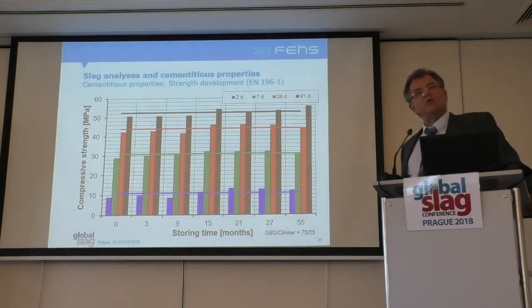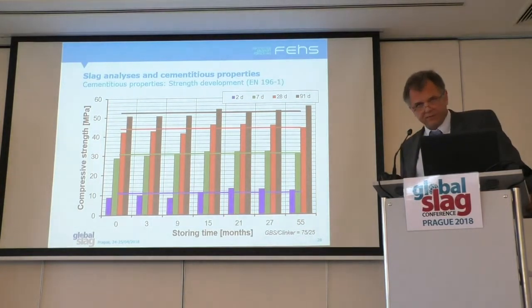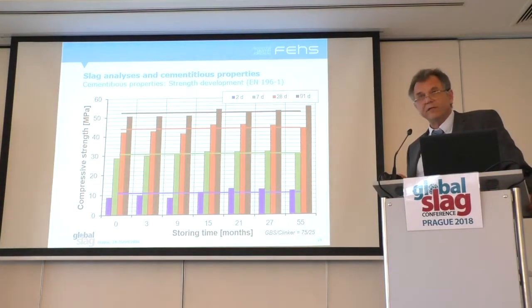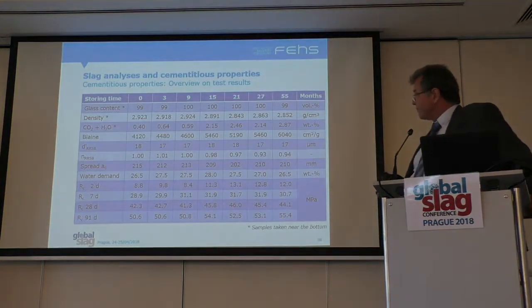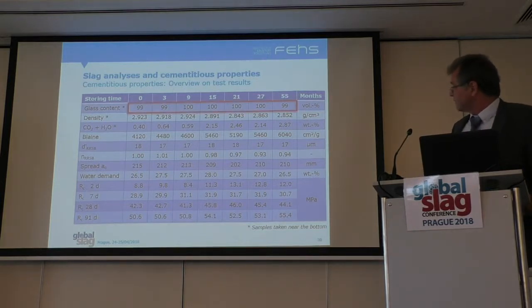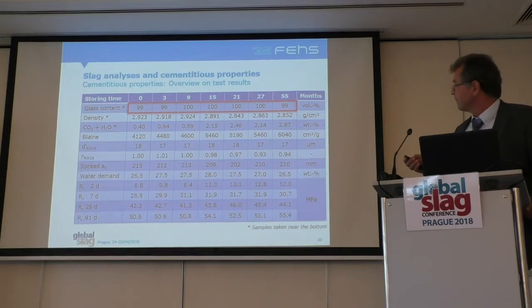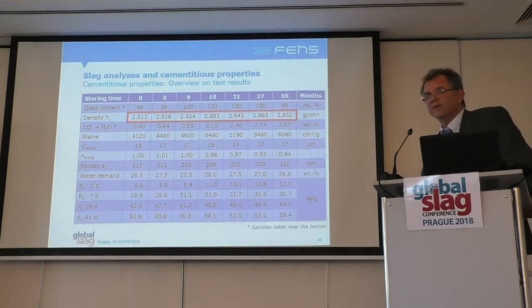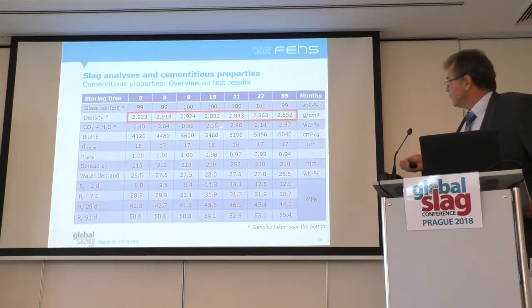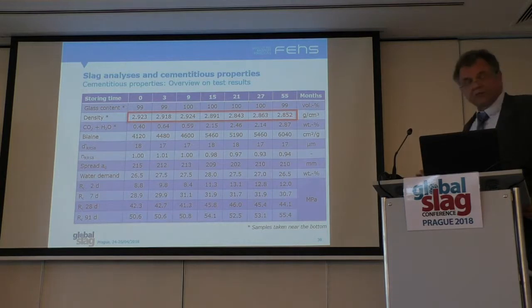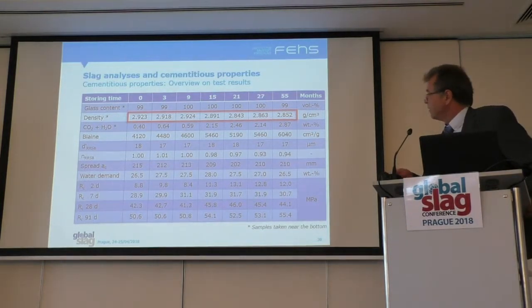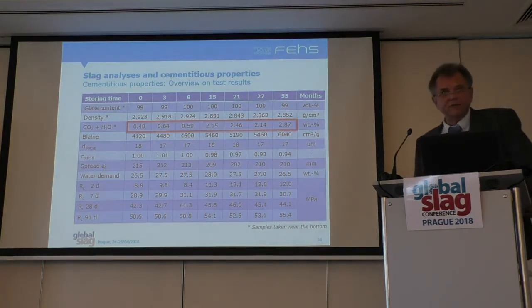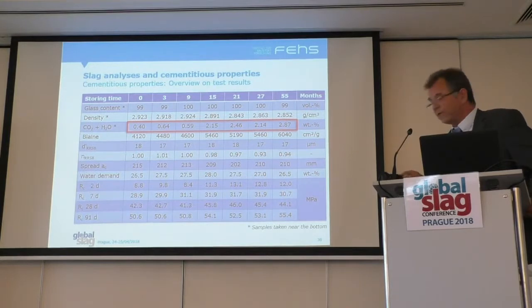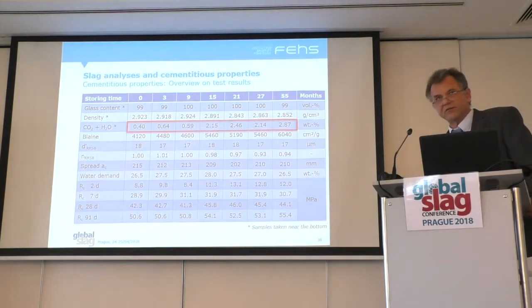That means there is no loss in strength. There is no less reactivity if you guarantee that you have really a comparable fineness, not a comparable Blaine value, but a comparable fineness. All results in one table. Glass content not affected. Density is a simple to be measured parameter. Due to the prehydration, you find a decreasing true density of the material. Strongly increasing contents of water and CO2. Very good and easy to measure indicator for the age of a slag.